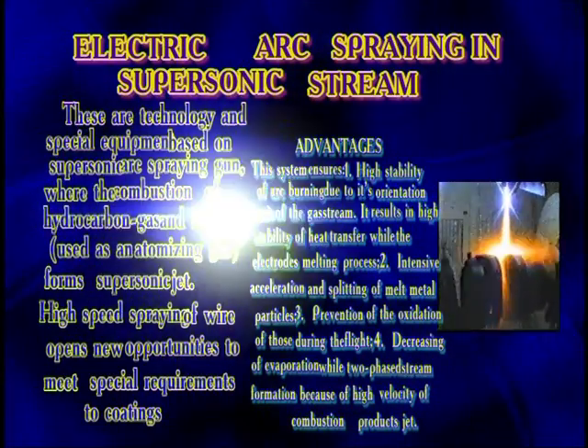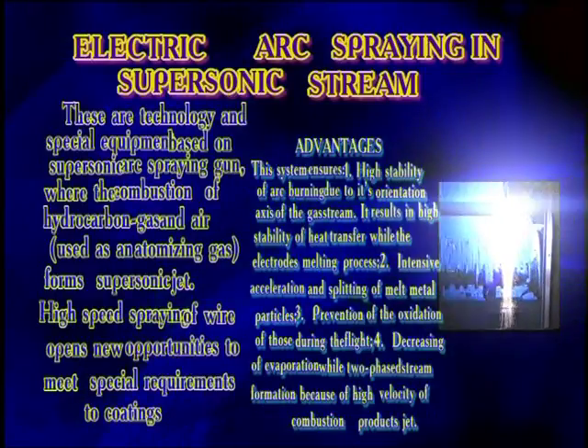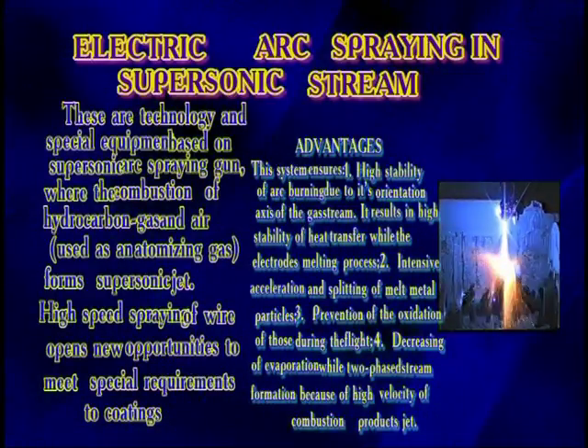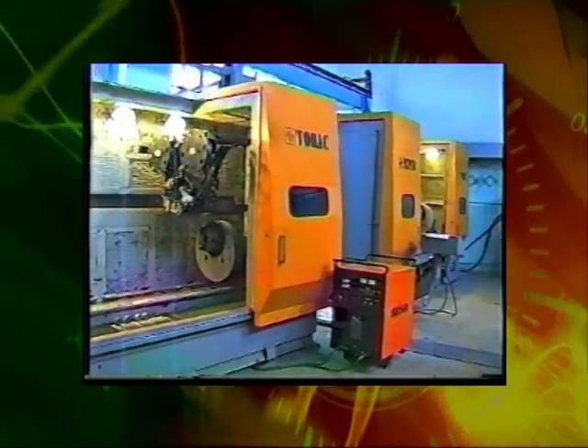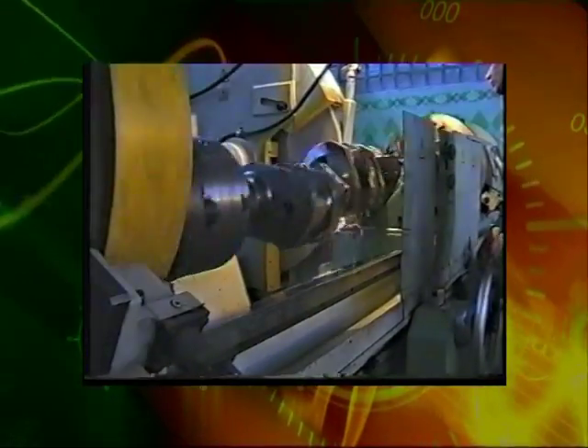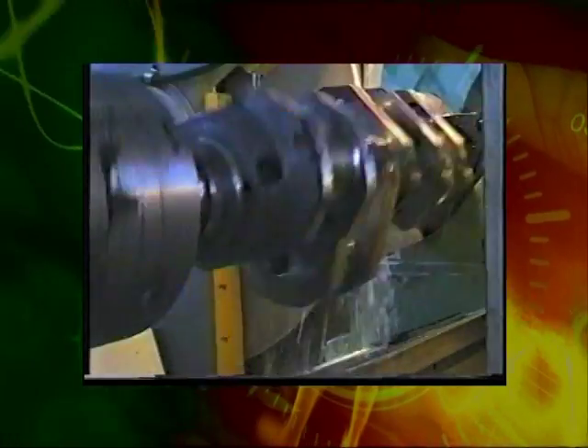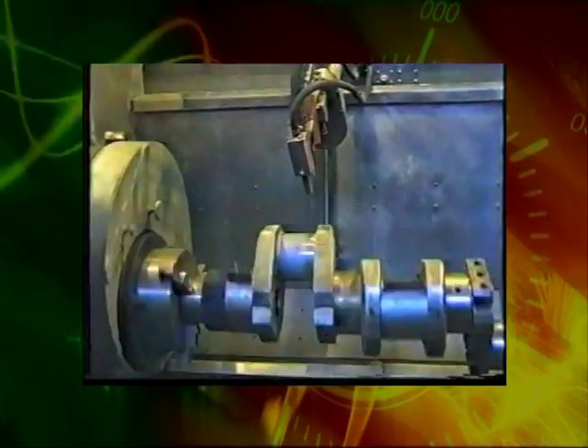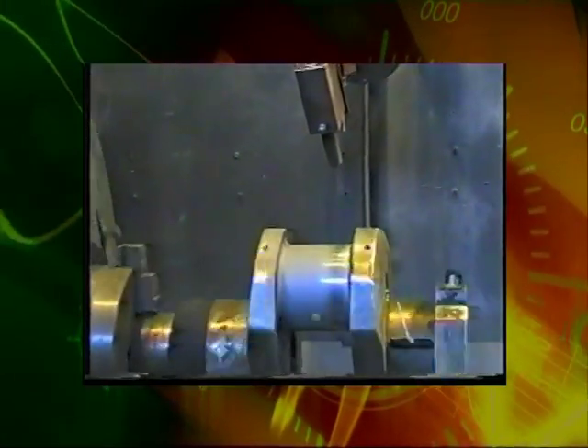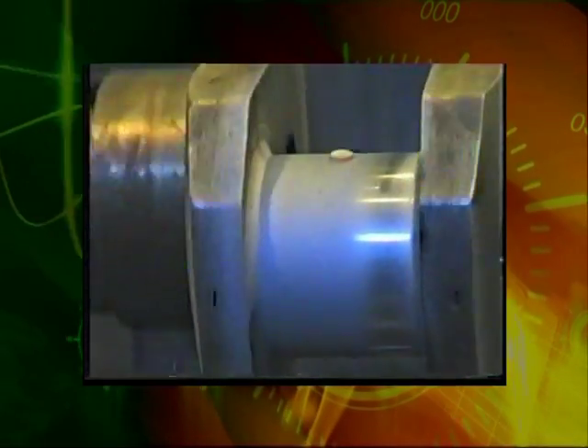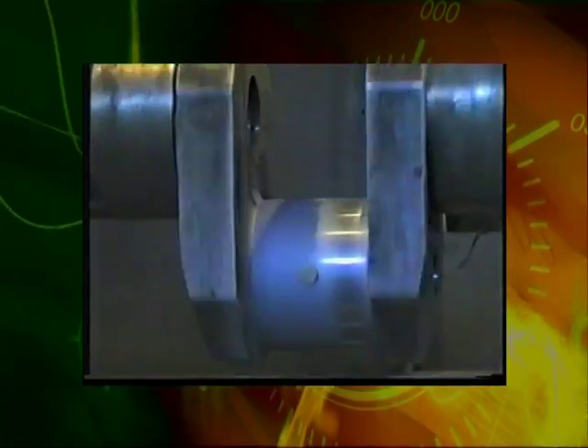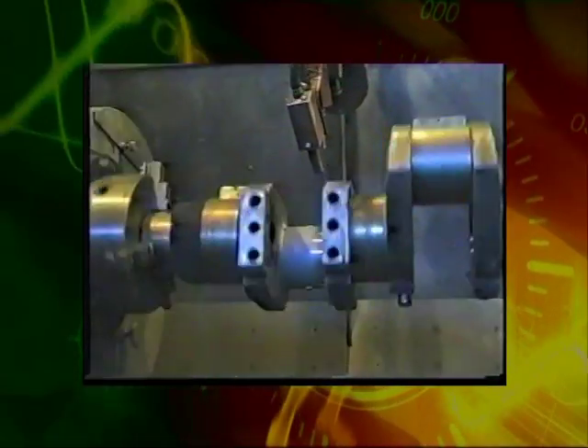Developed is the technology and specialized equipment based on the supersonic arc spraying gun, where the supersonic jet of combustion products of hydrocarbon gas with air is used as a spraying gas. New possibilities for satisfying the special requirements to coatings on parts are opened by high-speed wire spraying. This is provided due to raising the kinetic energy of particles under spraying, increase of their concentration in metal flows, and lowering of the spread of parameters such as velocity, temperature, and sizes in the vicinity of the substrate. This determines increase of adhesive and cohesive strength of coatings, decrease of oxidization, and improvement of stability and reproducibility of their properties.